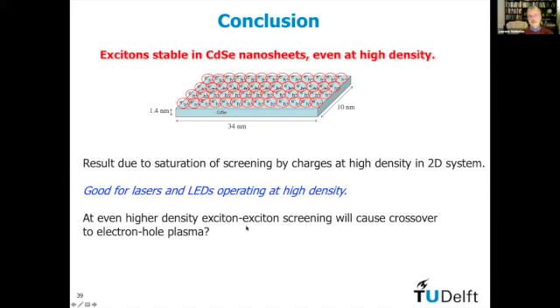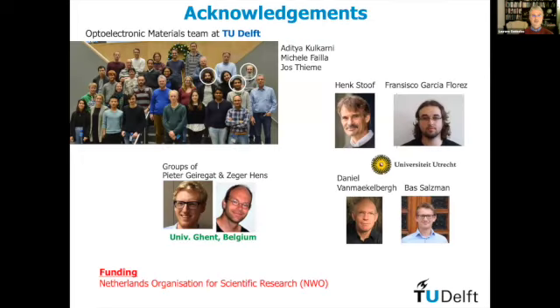And we think that at an even higher density, at some point you should get a crossover to an electron-hole plasma, because the excitons also start screening each other, and I did not take that into account. We only took into account so far the screening of an electron and a hole in an exciton by free charges moving around, but excitons mutually also screen each other, because the dielectric constant is reduced when an exciton is surrounded by many other excitons. That's also future work.